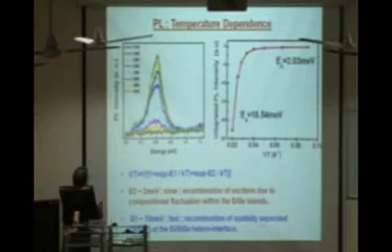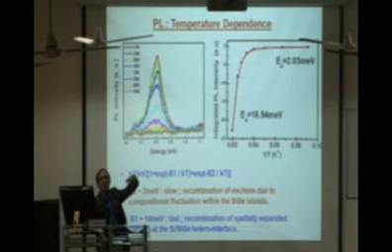What we want to show is that this emission energy shifts as a function of the size of the material, what is called the quantum size effect. That is one direct proof: if you get a size-dependent shift of the luminescence or the optical absorption of the emission peak, you know that this material has entered the so-called quantum region. Only thing, as you see, the peak is very broad because of the size distribution of those quantum dots. In fact, this luminescence typically exists only up to about 40 Kelvin or maximum 50 Kelvin, because the exciton binding energy is very, very low.